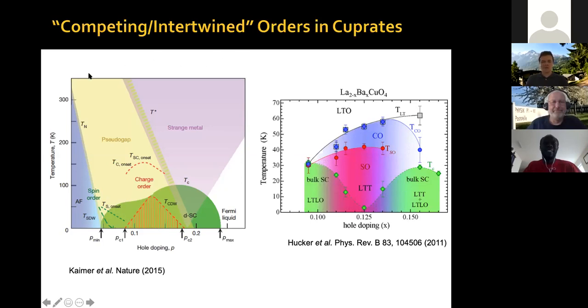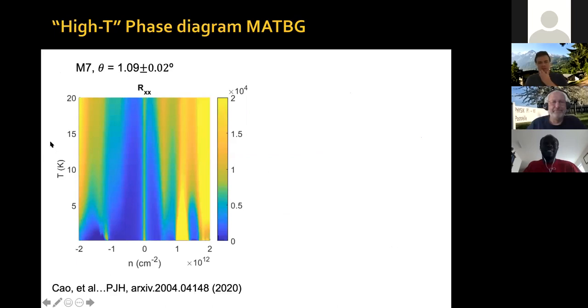So now let me show you what we measure in magic angle graphene. This is a higher temperature phase diagram than I was typically showing yesterday, in magic angle graphene. This is for a device with a twist angle of 1.09 degrees. Now this is temperature up to 20 Kelvin. This is density. This is charge neutrality.